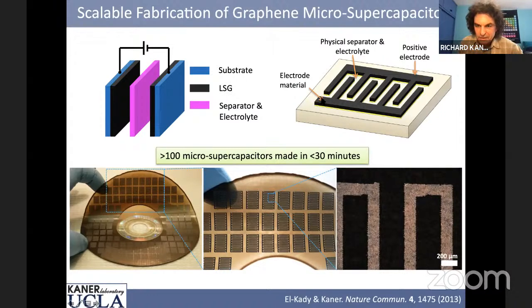And so we're just simply going to have two electrodes, one positive, one negative. It makes no difference which we want. We can switch them around. And you can see the laser converted graphene. It's dark, it's conductive. You can see the graphite oxide. We're using that as the insulator. We can just put a drop of electrolyte, and this will work quite well.